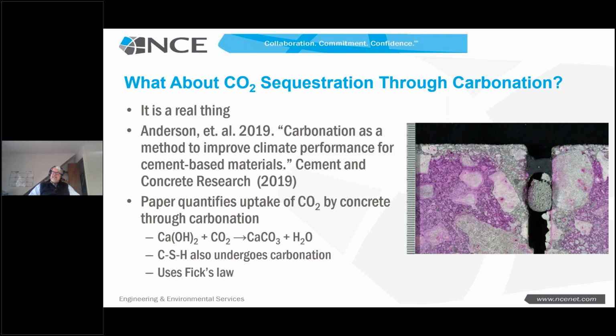So if we get into something like in service, one other part of the PCA plan that's very important is carbonation. And I think what we have to realize about carbonation is, we talked about the fact we took limestone, we put it in a kiln, we burned it, we created calcium oxide, and we released CO2. Well, that CO2 is out there. It wants to get back together with that calcium oxide, and it will over time in a concrete structure. So the concrete structure begins to carbonate.